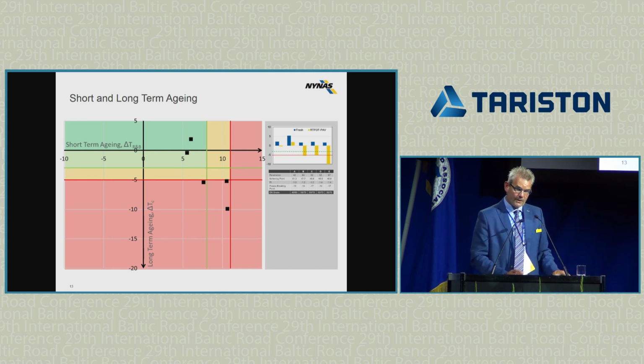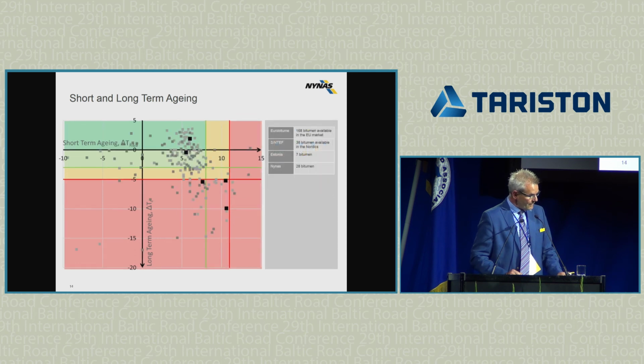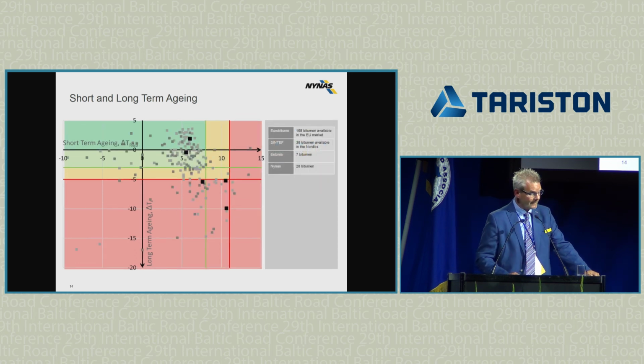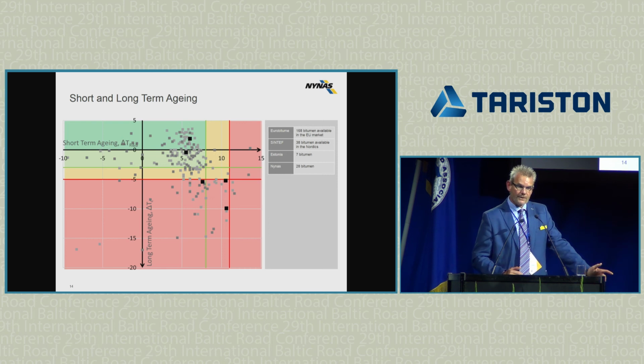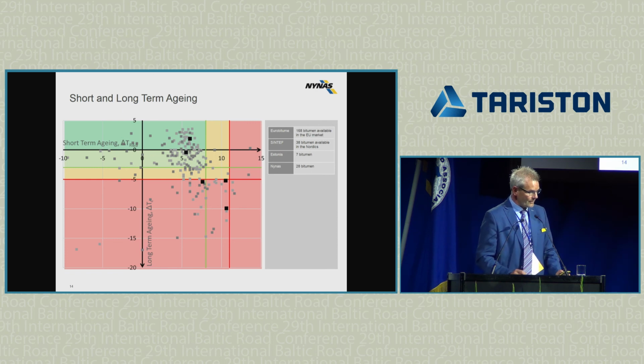Now, these are just the 5 bitumens from our experiment, but from the databases that we have available, we plotted the number of European bitumens. And this is what you see. It's quite striking. Most of the bitumens meet the short-term aging requirement, but the differences that we see in these materials when it comes to delta TC, it's remarkable. Some materials go down to minus 17. And these are really materials that are at severe risk of cracking early life in the pavement. This is a data set that contains both modified bitumens and standard paving grade bitumens. So it's quite a remarkable difference in the performance in terms of long-term aging resistance compared to short-term aging resistance.